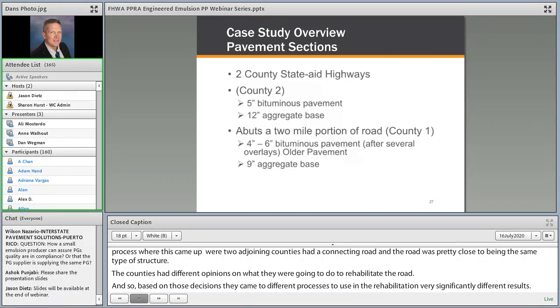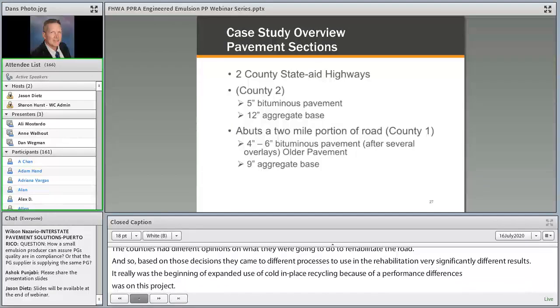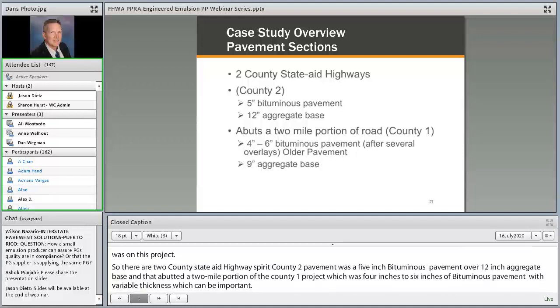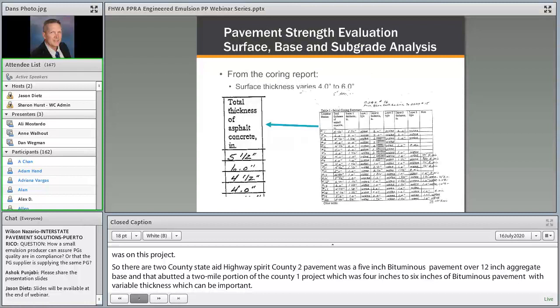So there's 2 county state aid highways. County 2 pavement was a 5-inch bituminous pavement over a 12-inch aggregate base, and that abutted a 2-mile portion of the County 1 project, which was 4 to 6 inches of bituminous pavement. It was variable thickness, which can be important in the process selection. It was an older pavement that had been overlaid a couple times and had 9 inches of aggregate base. So really, when you look at it from a pavement structural standpoint, they're pretty close to being equal.